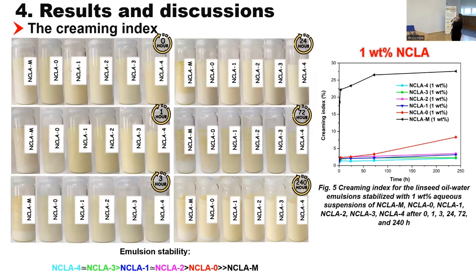The same results remain valid when a higher concentration of cellulose nanofibers was present in the emulsions. However, we can see a more accentuated, faster tendency of destabilization. This may mean that an excess of nanocellulose was present at the interface between oil and water. And since we all know that nanocellulose has the tendency to self-associate and self-aggregate, this could have led to the coalescence of the droplets in the emulsions and hence the lower stability at higher concentration of nanocellulose.